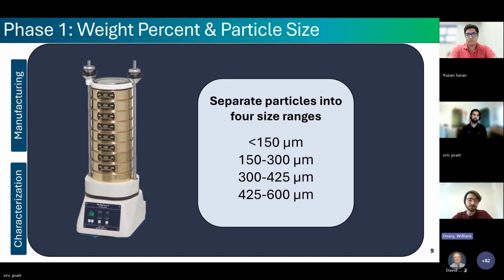So to isolate the 4 size fractions for our matrix, we sieved our jet milled material using a Ro-Tap Model E mechanical shaker, and this had a stack of sieves corresponding to our target ranges, which were less than 150, 150 to 300, 300 to 425, and 425 to 600 microns.